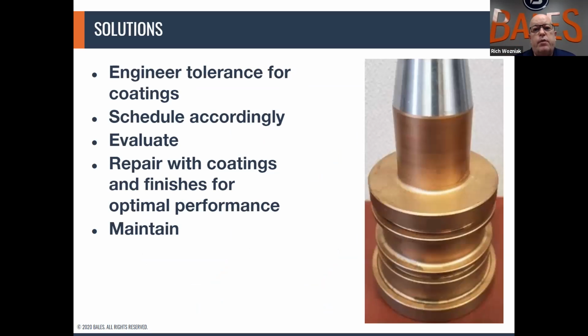Some of the solutions we have here: engineering tolerances for the coatings will definitely help. If you know that you've got some changes in resins or tough materials, build in that tolerance, especially if you have a tight tolerance in a tool, so that you can get away with a slightly thicker coating, looking at 3 to 4 tenths instead of 1 to 2 tenths per side.